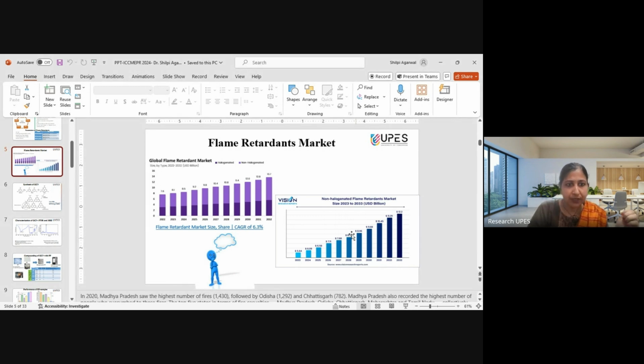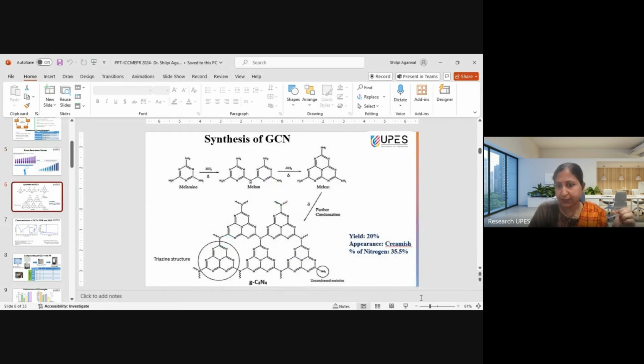So we worked on the development of a synergist for the flame retardant. We developed graphitic carbon nitride from melamine. It was pyrolyzed at high temperature, around 500 degrees centigrade. We heated it in the absence of oxygen, so it condensed and polymerized to graphitic carbon nitride. It has a two-dimensional structure, more like graphite, and the different layers are joined together by weak van der Waals forces.